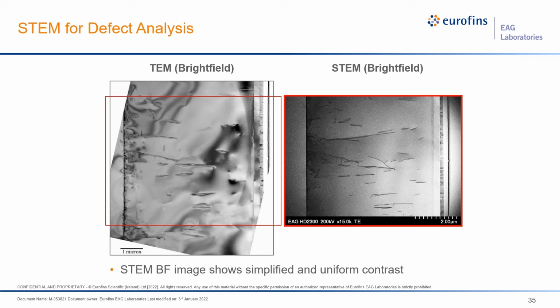So are they screw, or are they edge, or are they mixed, for instance? And so we like to use STEM for this task versus just conventional TEM bright field, because the STEM bright field images show much more simplified and uniform contrast than the TEM. So in the TEM, you've got some thickness fringes and bend contours. This is the exact same sample imaged in TEM and STEM here, and you can just see how much simpler the contrast is in the STEM, and how nice the background versus the defect is, right? So it really makes it easy.